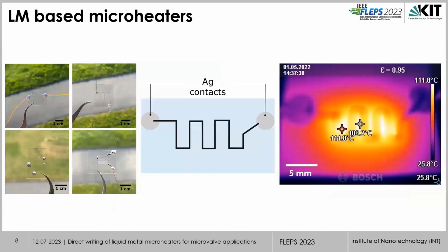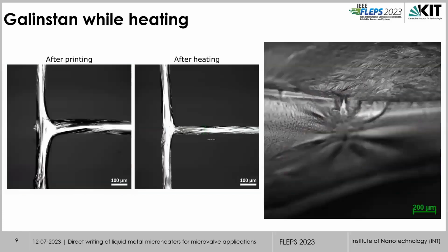So now I come to the microheater part. We use this direct writing of liquid metals for fabrication of microheater structures. We fabricated different designs and different architectures in microheater structures. We use this silver-based epoxy for contact pads, and monitor the temperature on the surface while applying a bias with this IR camera.